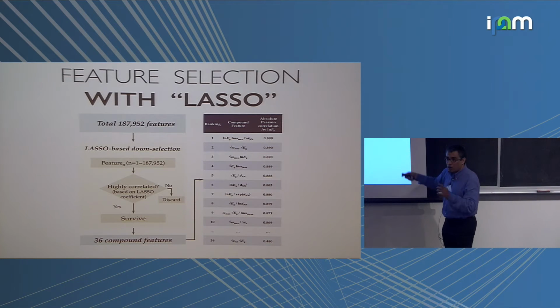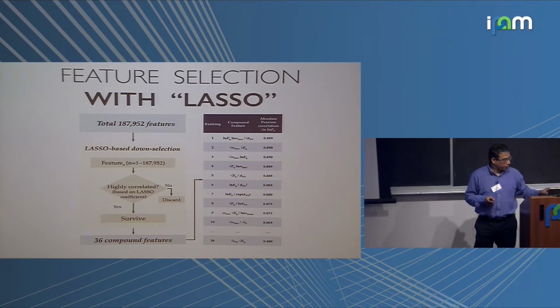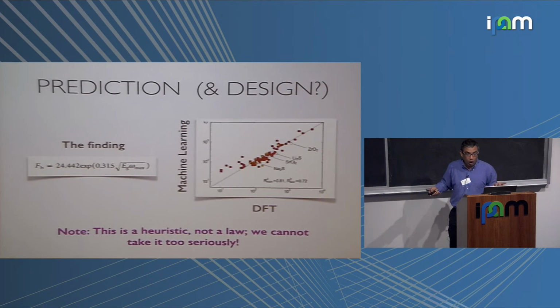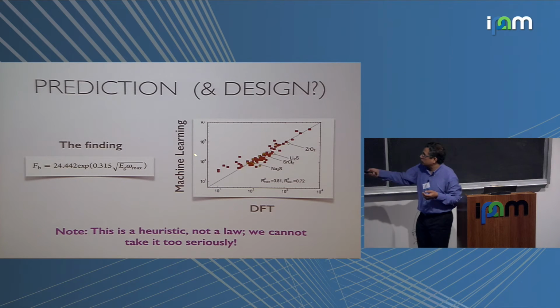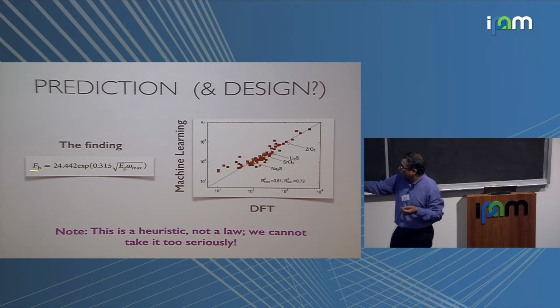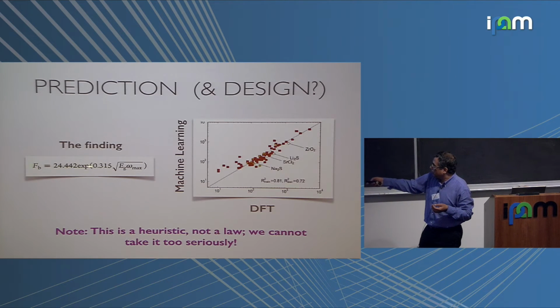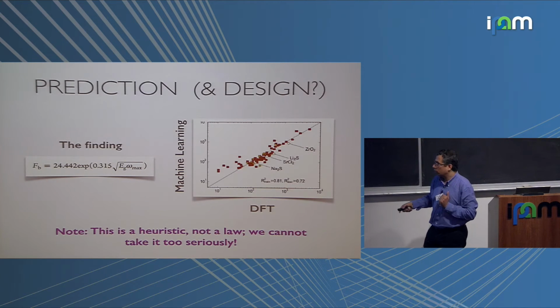Square root of the highest phonon frequency that the material experiences, times the square root of the band gap. Right? So now I'm going to show you how actually the correlation works. So this is the machine. So this is the formula. The breakdown field is related to the square root of the band gap times the phonon cutoff.